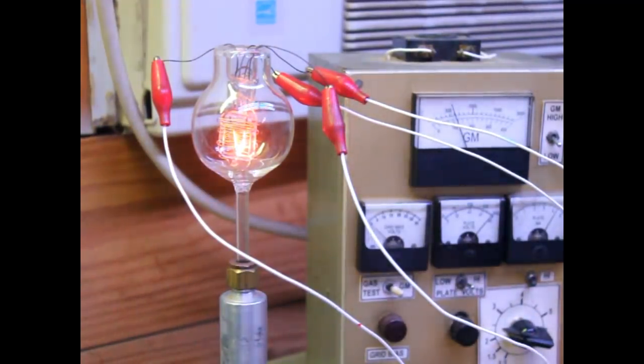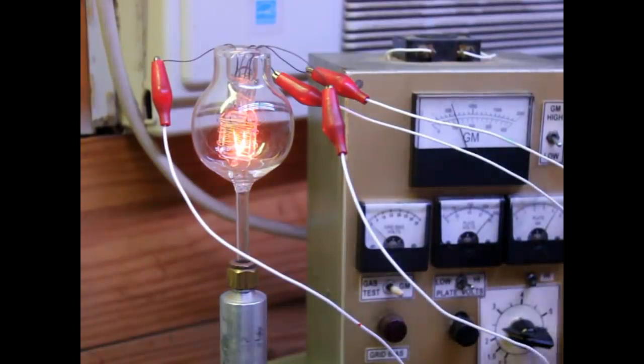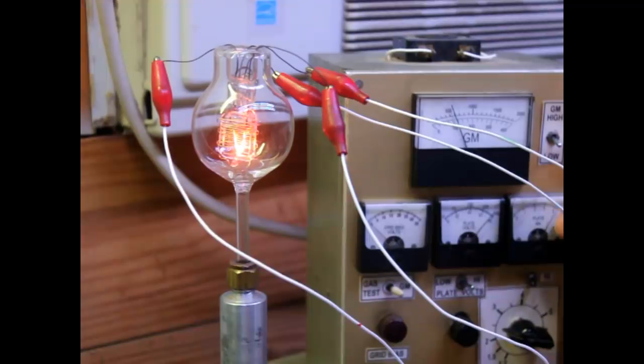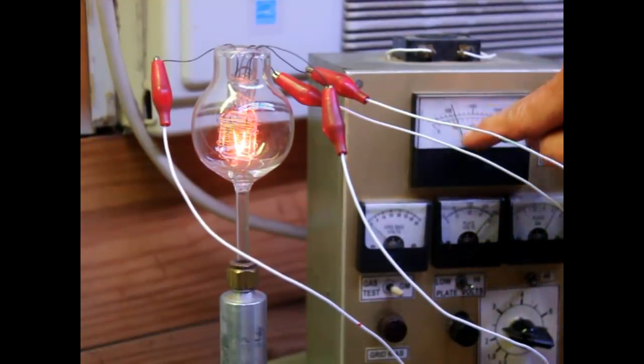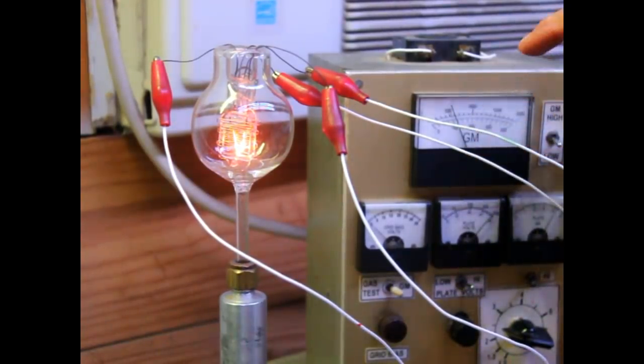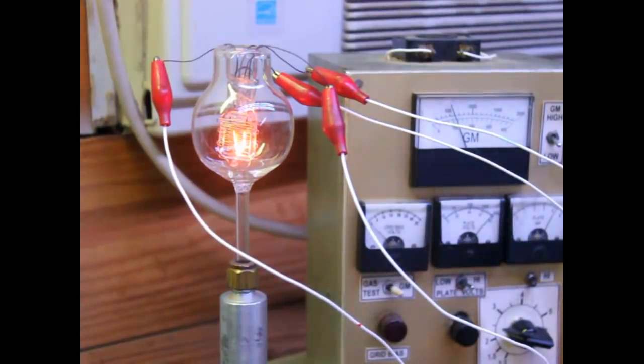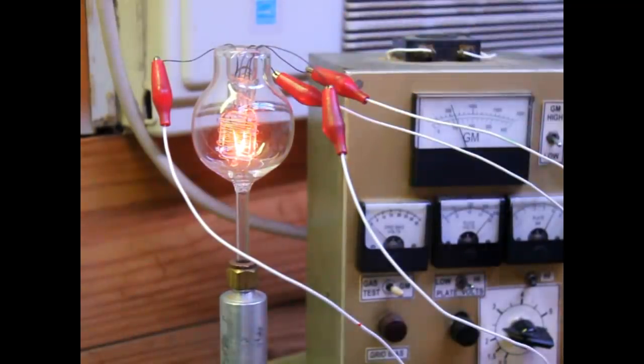Okay. So, we're running 300 volts on the plate and about 2.5 volts on the filament. We have a plate current of 4 milliamps and a transconductance of just over 100, about 120. So the tube is working quite well. It's taking high voltage to make it work because the spacing between the plate and the filament is great. It's quite large. Okay?